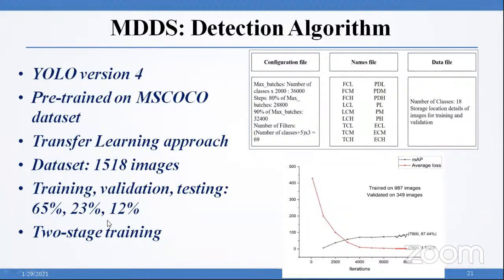Since the transfer learning approach was adopted, we used the pre-trained weights of YOLO V4 on the MS COCO dataset first, and the network was trained for about 1000 iterations, so that the weights at each neuron would be updated to the actual problem, that is, to detect for the MDDS. After 1000 iterations, the modified weights file was used for training the network again.